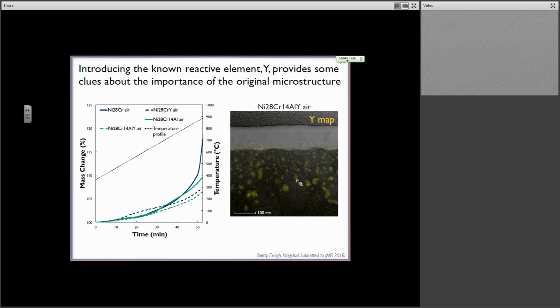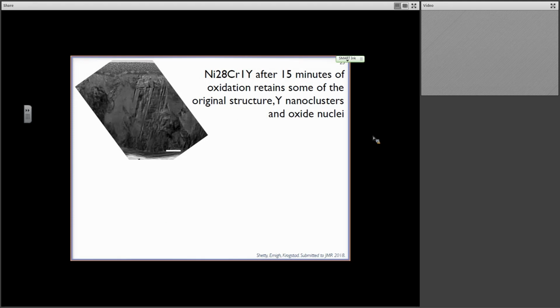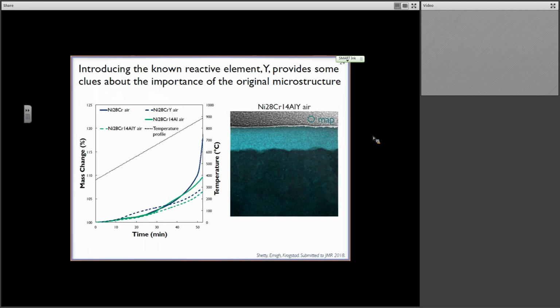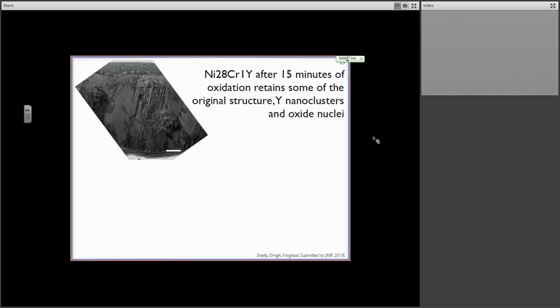So we were worried that we had some internal oxidation. Yttrium has a high affinity for oxygen. Perhaps we're just forming little oxides. But we don't see any evidence of that either. You can see here that the oxygen, to within the ability of quantifying oxygen via EDS, we don't see any significant oxygen uptake in the alloy itself, just in the film. Now I will argue this is most definitely aluminum oxide. I'm not going to show you those chemical maps because I really want to focus on the role of yttrium here. Now, this is all quite interesting, but we really wanted to understand what was going on with these little yttrium clusters. And so we went back and we did some shorter oxidation steps.